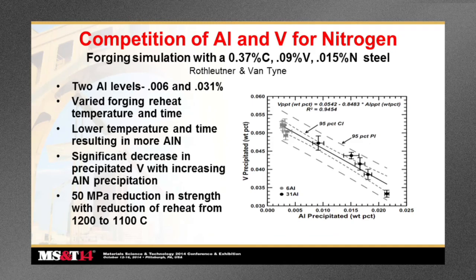Here's another example of the effect of aluminum on interfering with the vanadium nitrogen system. This is work done by Roth-Lutner and Van Tine, where they were doing forging simulations using a base alloy of 0.37 carbon, 0.09 vanadium, and 0.015 nitrogen, and it had two aluminum levels they were looking at, 0.006 and 0.031% aluminum. They varied the forging reheat temperatures and times to get various amounts of aluminum nitride formation in the austenite prior to the forging and cooling step.